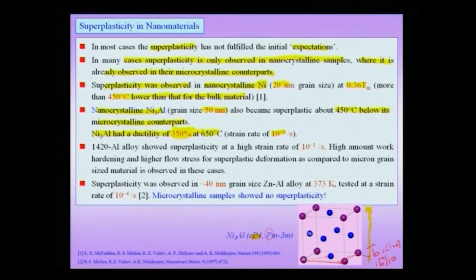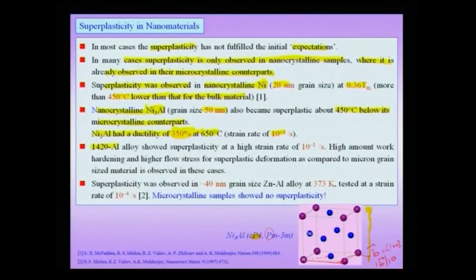So, therefore, we are able to see superplasticity at reduced temperature in a pure material like nickel, but also in an intermetallic like Ni3Al. In the case of 1420 aluminum alloy, it showed superplasticity at a high strain rate of about 10 power minus 1 per second. A high amount of work hardening and higher flow stress for superplastic deformation as compared to the micron size sample is also observed in these cases.